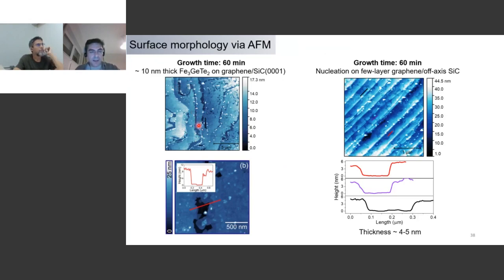Meaning that even if you change one layer of graphene on your substrate, this influences the growth directly, where I need a much longer time to grow on the bilayer graphene areas in comparison to the monolayer areas. So, the light blue areas here is where FGT is covering, right? And one test that we did was the following.